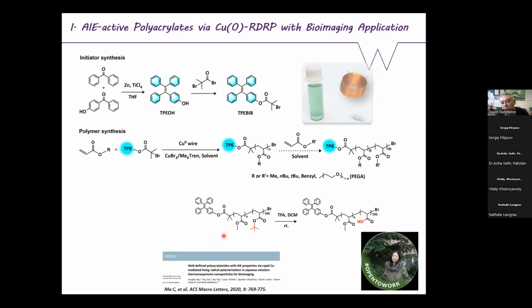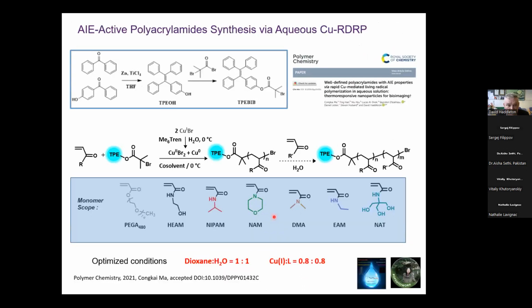So what we're doing here is making methyl acrylate and tertiary butyl acrylate, and then chopping up the t-butyl acrylate to get our hydrophilic-hydrophobic block copolymer. Dispersity of these is less than 1.2, usually less than 1.1. There's pretty much zero termination doing it like this, and so you can imagine we would self-assemble this and it would be emissive because it aggregated. We can then do this in water as well.